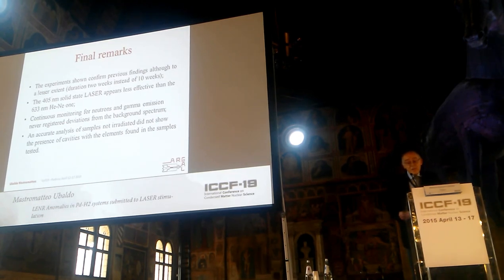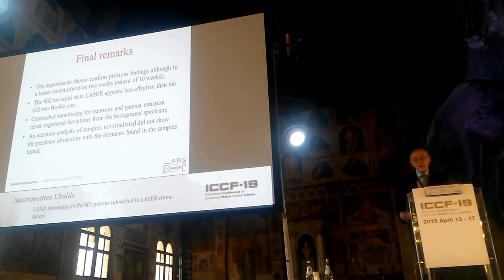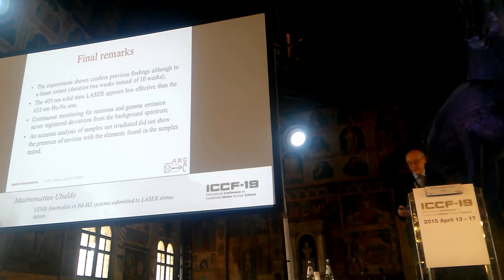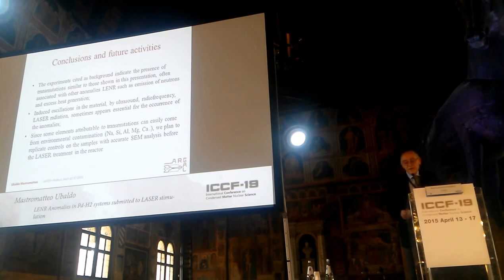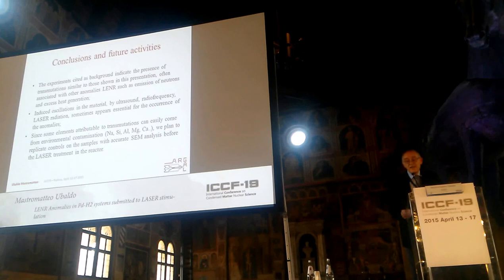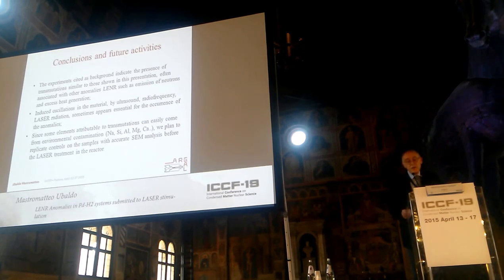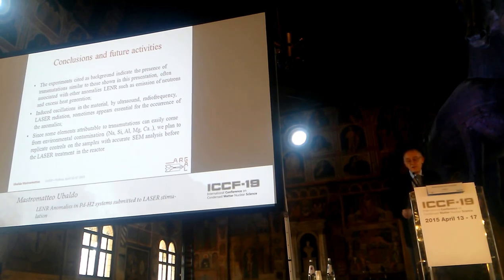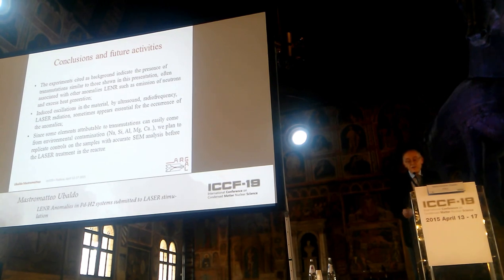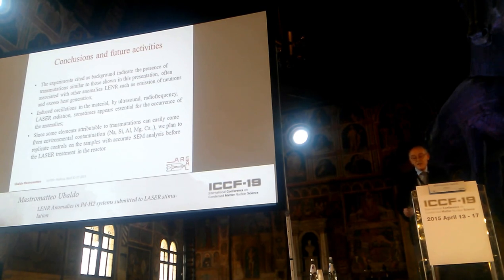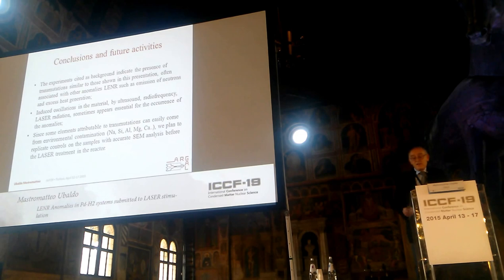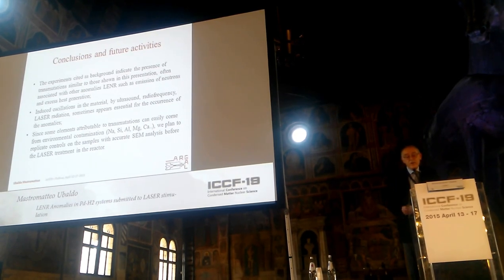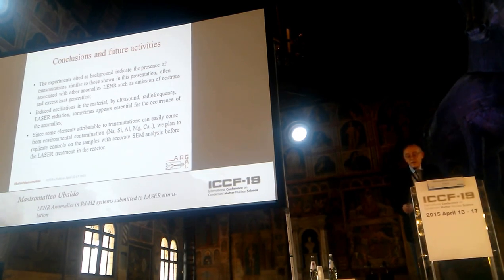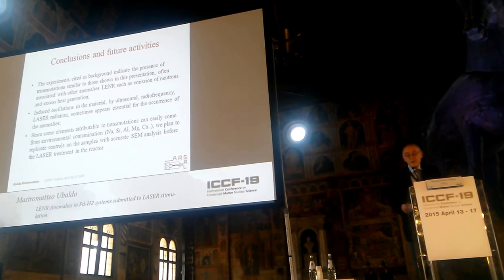An accurate analysis of samples not irradiated before irradiation did not show the presence of cavities with the elements found in the samples tested. And so, to conclude, the experiments stated as background indicate the presence of transmutation similar to those shown in this presentation, often associated with other anomalies, neutron emission and excess heat generation. Induced oscillation in the material by ultrasound, radiofrequency, or laser radiation sometimes appears essential for the occurrence of the anomalies. Since some elements attributable to transmutation can easily come from environmental contamination, this is to be underlined, we plan to replicate controls on the samples with accurate SEM analysis before the laser treatment in the reactor.